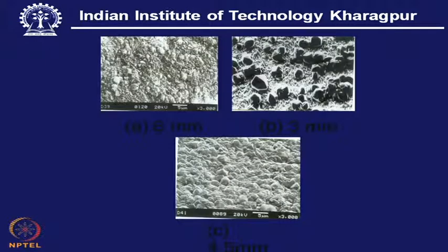Now, how are we going to look into this? Let us examine what we see. This is actually a secondary electron microscopic image of a diamond coating. So, these are the diamond crystals. Through this SEM image, one should be able to recognize these fine crystals which are part of this coating, and this is deposited by the hot filament technique.